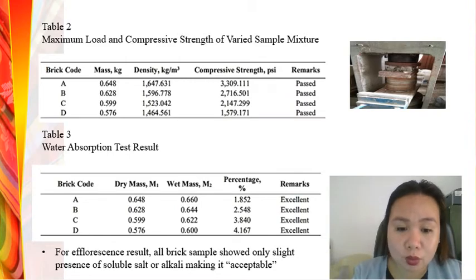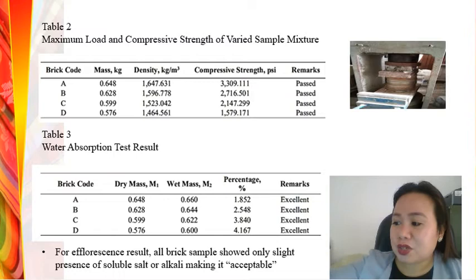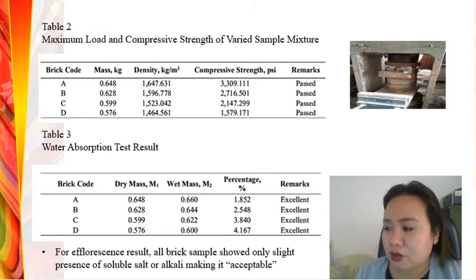In terms of the efflorescence test, a whitish crystalline deposit of soluble salts or crystals on bricks, consisting of calcium sulfate, magnesium sulfate, and carbonate of sodium and potassium, is called efflorescence. Sometimes efflorescence appears a few years after the end of construction, leaving the building owner to face questions about cleaning or maintenance. The water will tend to dissolve the soluble salts in the brick and transport them to its surface, where they may be progressively deposited as the water in which they are dissolved evaporates.